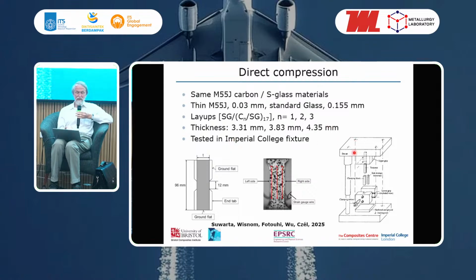They were tested in this Imperial College fixture, which is one of the better ways of testing compression. Compression testing is extremely difficult with composites because there's a risk of buckling. It's very difficult to get the load in without introducing shear and other failure modes. This is probably the best method of doing direct compression tests. And these specimens had a DIC pattern to measure the strain, and then they were loaded in compression.